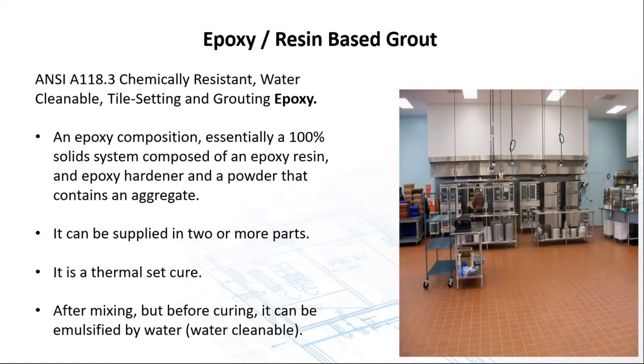118.3, this is your chemically resistant epoxy. It's essentially a 100% solid system. Generally has an epoxy resin, a hardener, and a powder that contains an aggregate. It can be supplied in two or more parts. It's a thermal set. After mixing, but before curing, it can be emulsified by water. So a few points here. It can be supplied in two or more parts. You have to mix the whole units at one time. I've been to different jobs where you've had some job site chemists trying to make a half bucket or mix a half bucket, and frankly, the installation has not been successful.